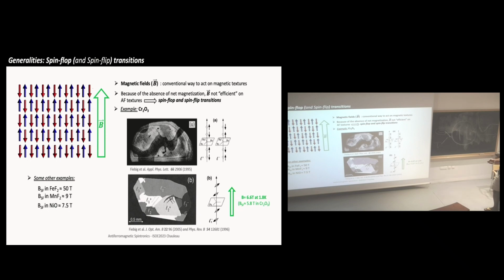So what is this image, actually? The question is what kind of technique we can use to visualize antiferromagnetic patterns. The reason it's difficult, again, is because there is no net magnetization, no stray field, so some conventional ways such as magnetometry will not work very well. MFM is quite difficult also, so we need to have some techniques.